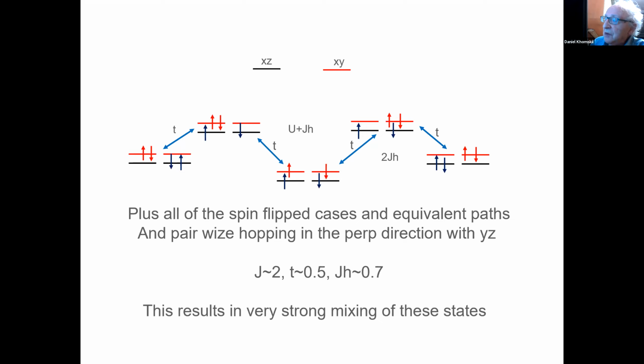Would it depend on the material, whether you are dealing with iron selenide or 122 or 1111, or would it be more or less the same in the whole class? I think these parameters are so sensitive that I can imagine changes, but the qualitative physics would be the same. I think this would happen all over, but by changing parameters, you can either go into the nematic phases, or a magnetically ordered phase, or a spin density wave phase, and maybe even a superconducting phase.